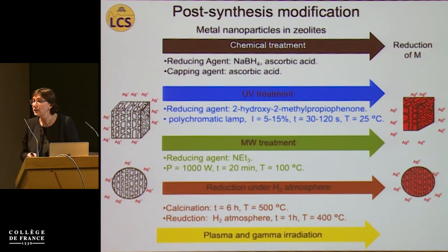Up to now, I showed you several examples of how zeolite nanocrystals could be synthesized via organic and inorganic structure directing agents, but we have also been interested in the post-synthesis modification of these nanocrystals. Under post-synthesis modification, we consider the incorporation of metal and semiconducting clusters in the pores. These metals usually are introduced in cationic form, but then under different treatments, either chemical treatment or plasma, gamma irradiation, microwave treatment, we have been able to reduce these cations to metals.